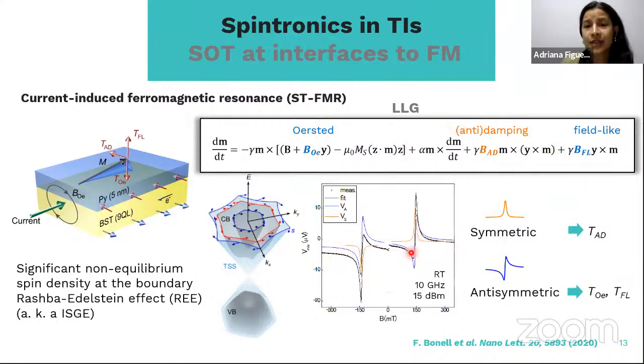This is the FMR signal that we see, and we have a component that is symmetric and a component that is antisymmetric. The symmetric component is what we call the damping or anti-damping. The antisymmetric component has two different contributions as well, which are torques. We have a diagram here. One is the Ørsted-like torque, and the other one is the field-like torque. The Ørsted-like torque is simply because we have a current passing through the sample. The field-like torque is the one that we're interested in, and we want that to be more relevant in our sample, because it comes from the Rashba-Edelstein effects at the interface. Those are a consequence of the spin structure at the interface of the TI.